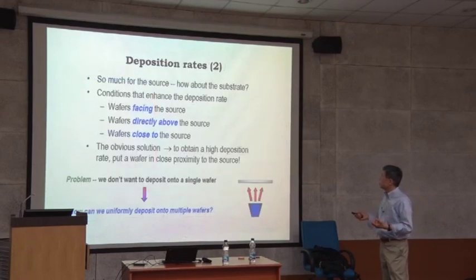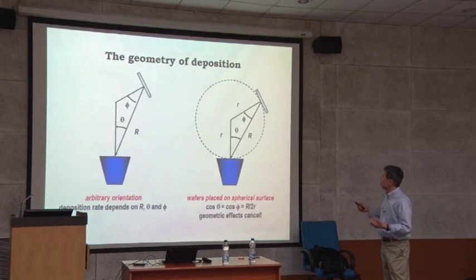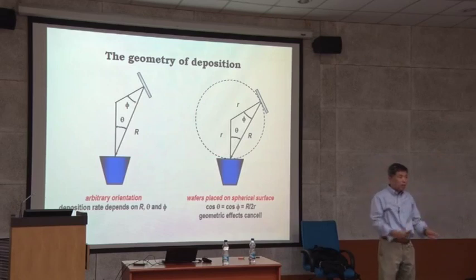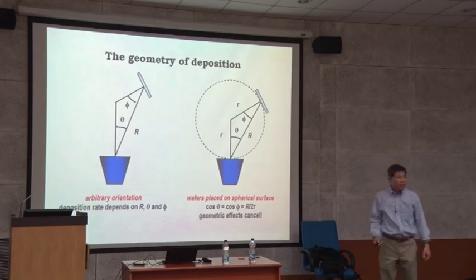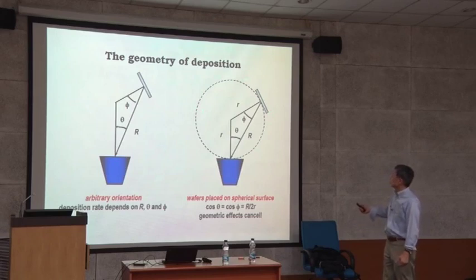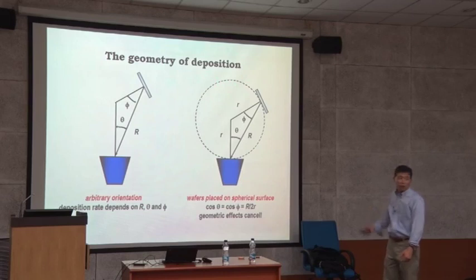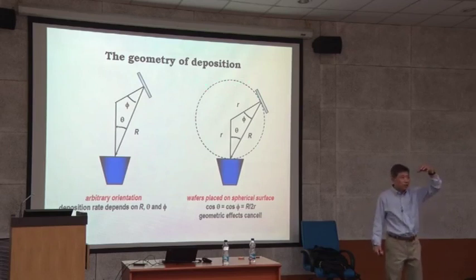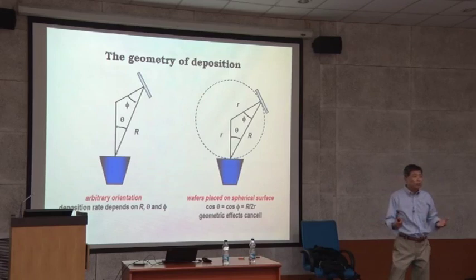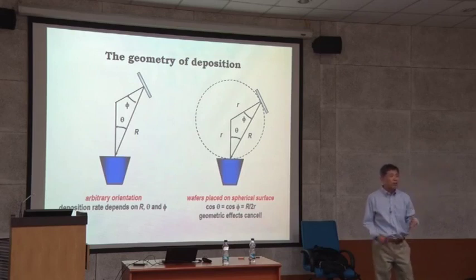So there are a lot of factors in deposition, but evaporation follows the cosine law. Okay? Cosine. So your rate is basically constant over here. You deposit on a quite flat substrate surface, and you get a thickness variation over here. Ideally you could use a curved substrate and get uniform thickness, but you cannot make a curved one. So with a further distance, you get better uniformity. But I don't think you have any issue for most of your depositions because your sample size is quite small, and your evaporation distance is that much distance. You have no issue. Okay? So that's what you do.